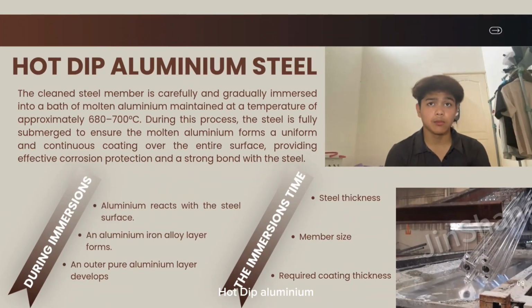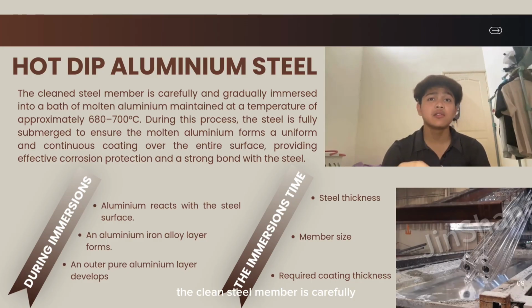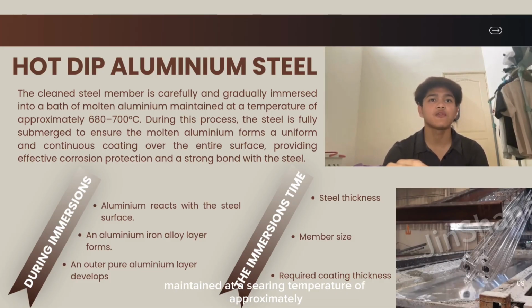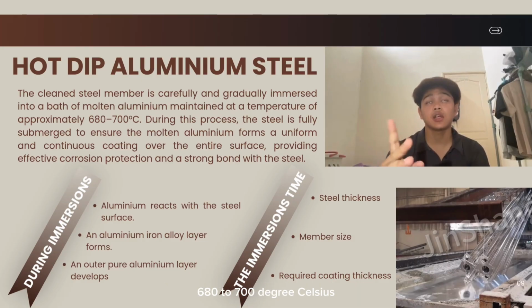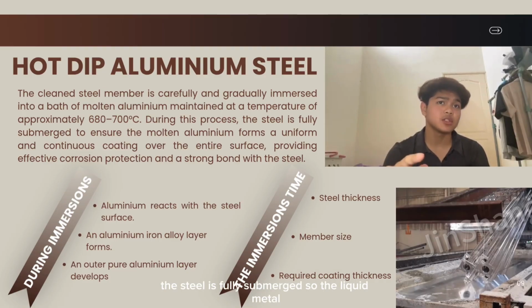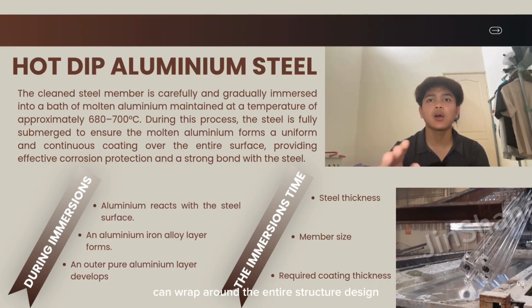Hot dip aluminium. We have arrived at a definitive transformation, the hot dip aluminium process. The clean steel member is carefully and gradually lowered into a bath of pure molten aluminium maintained at a searing temperature of approximately 680 to 700 degrees Celsius. To achieve total coverage, the steel is fully submerged, so the liquid metal can wrap around the entire structural design.